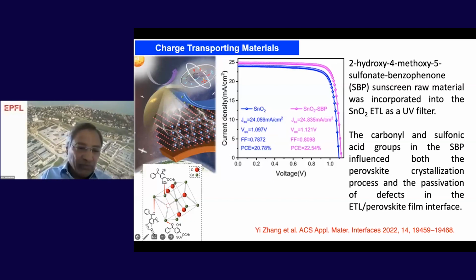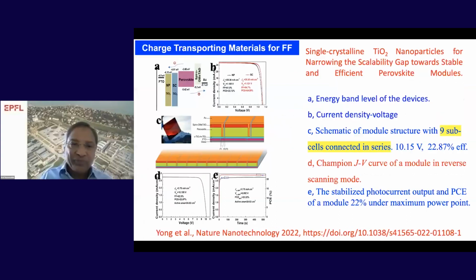So here what is happening is that this sunscreen material in the ETL layer has phenol and other groups, and these groups interact with the perovskite, forming a better interface between the ETL and the perovskite. This is a very interesting observation coming from our group, the improvement of the interface between the ETL and the perovskite composition.